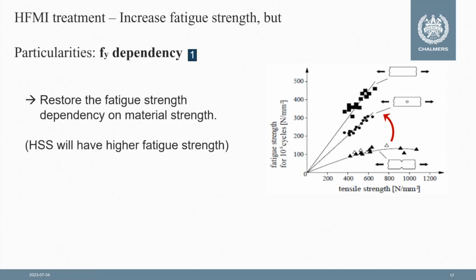Another implication, which is very important and a particularity for HFMI treated details that needs to be accounted for in design, is that we restore also the dependency of the fatigue strength on the material strength. So now having higher strength steel entails also having a higher fatigue strength. And that is a very important application, at least for new bridges, that would enable us in design of new bridges also to utilize the benefits of higher strength steel in many applications, which was, of course, not possible when just using as-welded details.